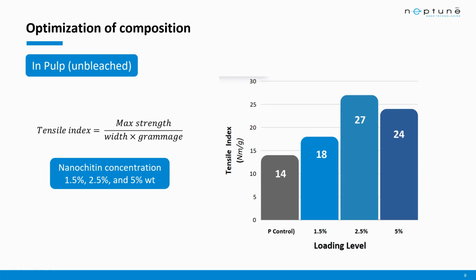So as you can see, there's actually a very large uplift of nearly 100% in tensile strength at the 2.5% loading levels. While a little bit of diminishing return has occurred at the 5% loading level, the uplift in tensile strength properties is still very significant.